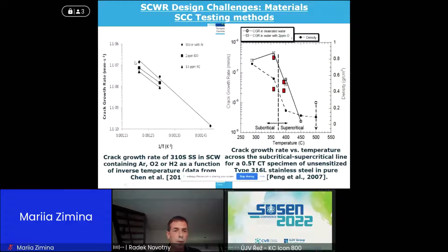But then we have another study on the left side, and these guys measured the exact opposite. They measured higher crack growth rate with higher temperature of supercritical water, and not depending on the composition of the material. So we definitely don't have enough information here.